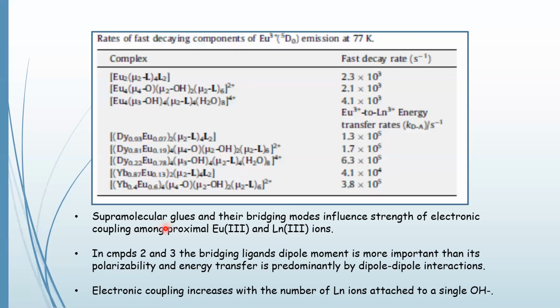In conclusion on that section, we concluded that supramolecular glues like oxides and hydroxides in these clusters, and the mode in which they are bridging, influence the strength of the coupling interactions among lanthanide ions. We were also able to show that the bridging ligand's dipole moment was more important than the polarizability, and that energy transfer involving these lanthanides is predominantly by dipole-dipole interactions. As I said before, we calculated the electronic coupling constants and showed that the coupling between the lanthanides would increase with the number of lanthanides that were attached to a single supramolecular glue moiety, like a single OH minus.